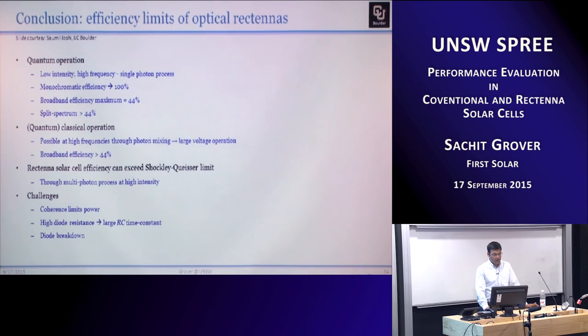But the key takeaways here are that yes, with monochromatic efficiency, best case, you can get 100%, but again, that's a far stretch from where we are today. Broadband efficiency maximum in the quantum regime is 44%. If you split the spectrum into different antennas, like a multi-junction process, you can go above 44%. If you are in a classical regime, which can be done through various techniques, you can again go above 44%. And thereby, we can exceed the Shockley-Queisser limit, but then really, the Shockley-Queisser limit is not valid if you are doing tricks like that.